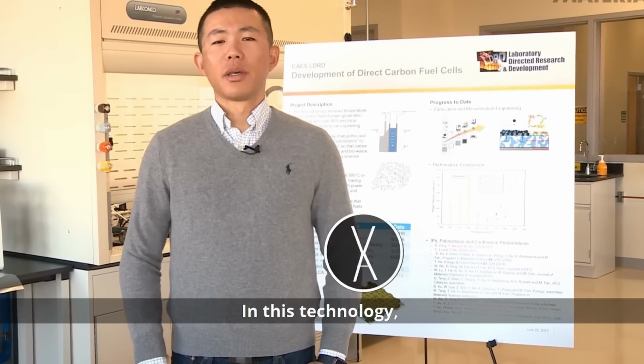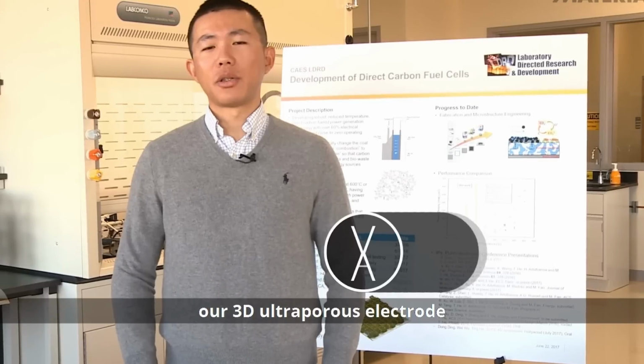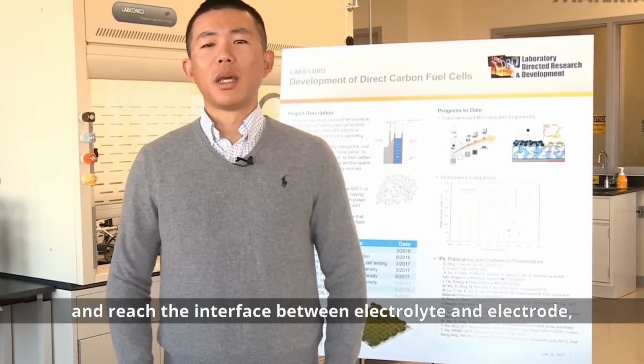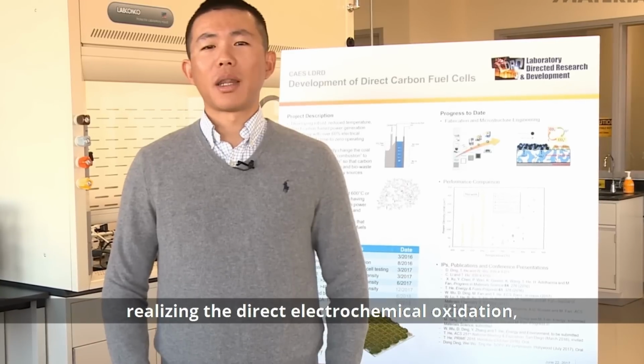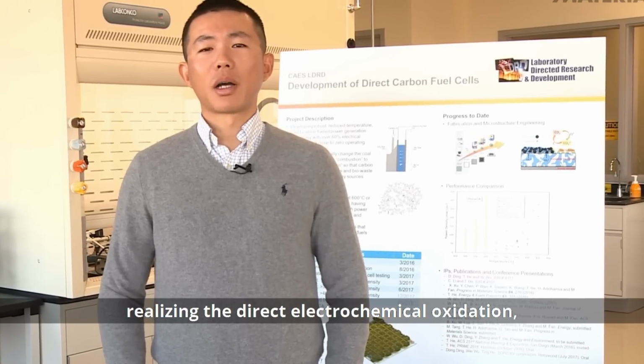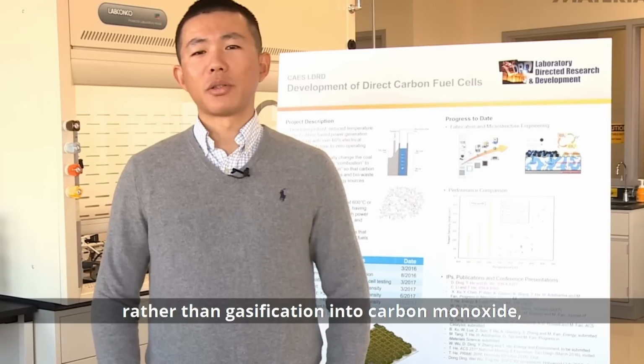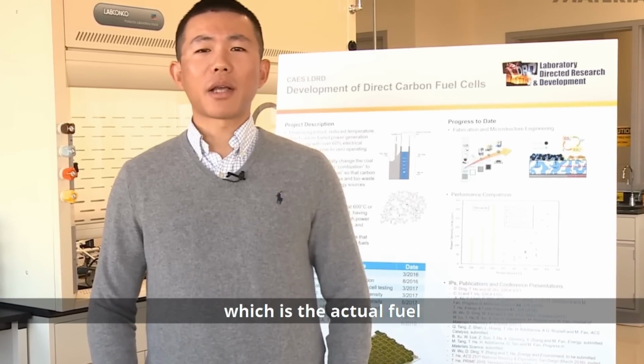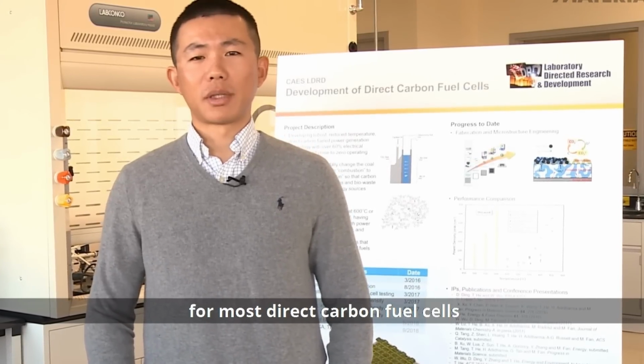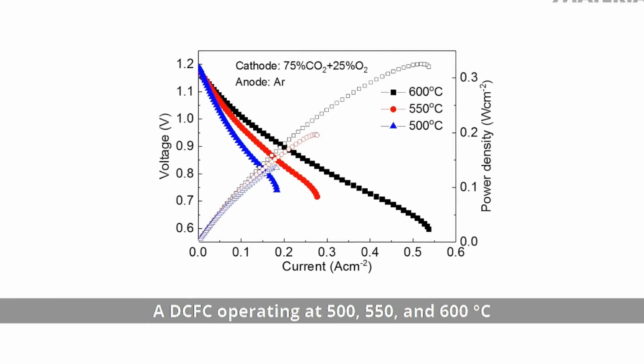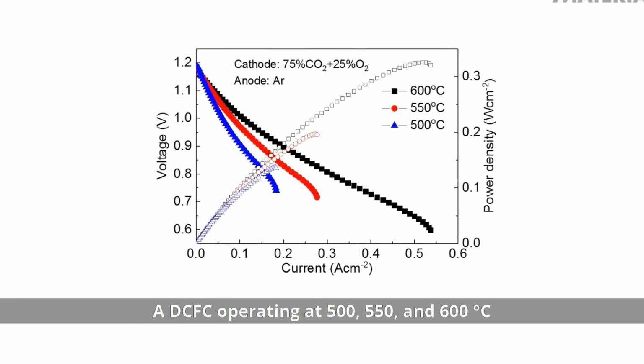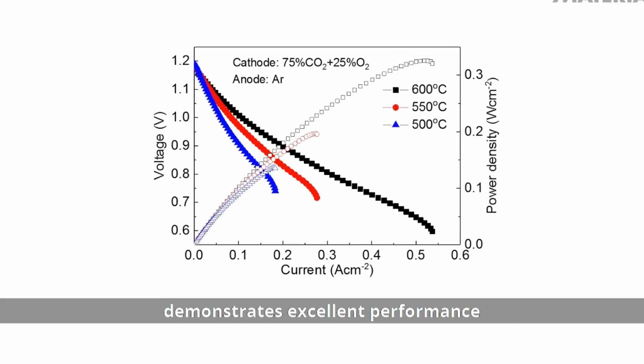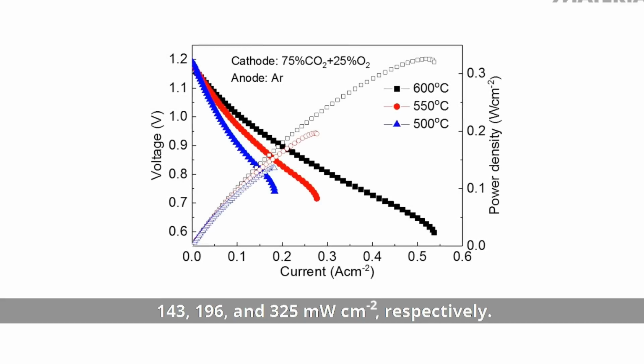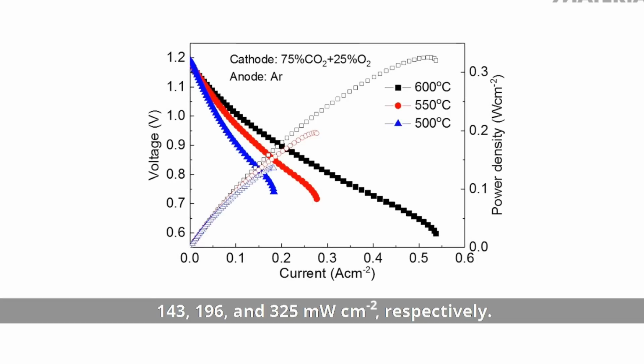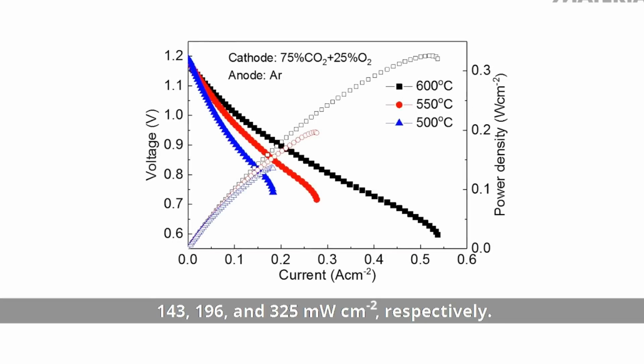In this technology, the solid carbon can readily go through our 3D ultraporous electrode and reach the interface between electrolyte and electrode, realizing the direct electrochemical oxidation rather than gasification into carbon monoxide, which is the actual fuel for most direct carbon fuel cells. A DCFC operating at 500, 550, and 600 degrees Celsius demonstrates excellent performance with maximum power densities of 143, 196, and 325 milliwatts per square centimeter, respectively.